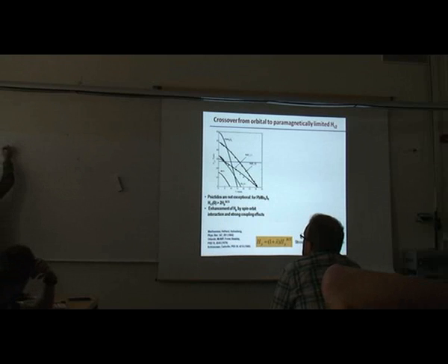paramagnetic field is enhanced by a factor of 1 plus lambda, and you can understand where it's coming from. It has all these formulas when you sum up all Matsubara frequencies. In the strong coupling limit, you multiply Matsubara frequencies by Z. Z is a normalization factor, and in the simple model it is just 1 plus lambda. So basically you multiply all temperatures by 1 plus lambda, and you get that. But there are 5 Fermi surfaces here, so 5 Z's.